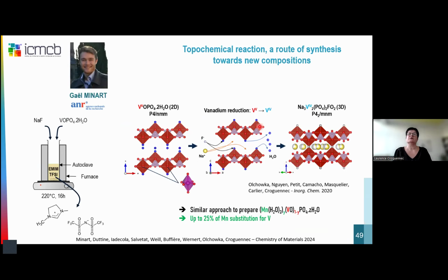And he was able, through these topochemical reactions that we had used a few years ago, to synthesize these NVPF oxyfluorine materials. In fact, by topochemical reactions using this vanadium-rich precursor, in ionic liquid media as source of fluorine, and also as media where we can do a hydrothermal, a solvothermal reaction at low temperatures, we really use these topochemical reactions with integration of sodium and fluorine in the structures, vanadium reduction and formation of these NVPF materials.